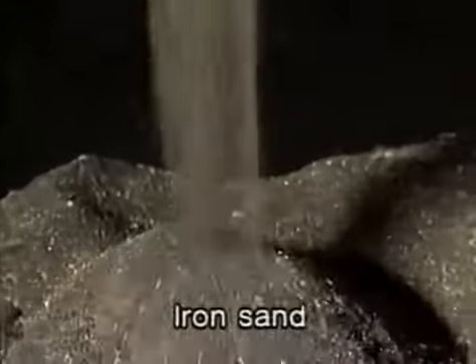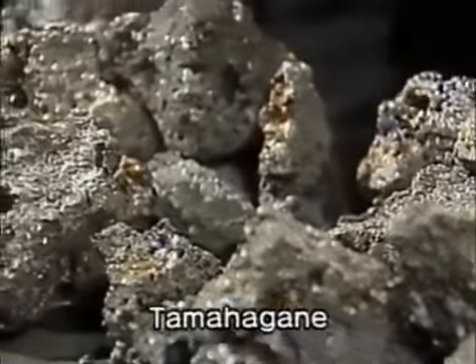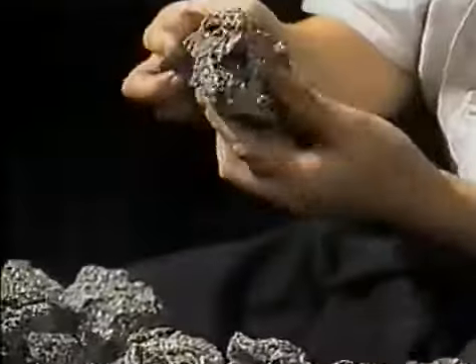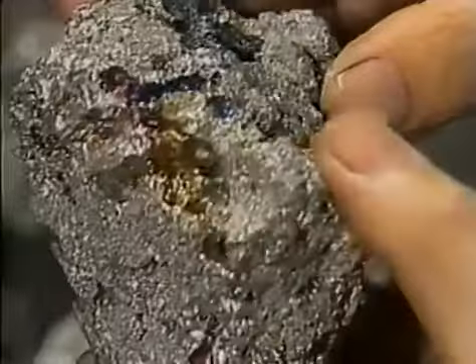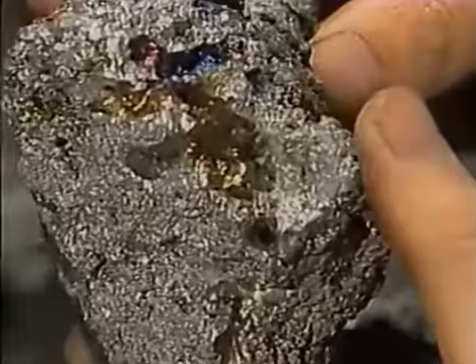The other key characteristic of Japanese swords is the use of a raw material known as tamahagane. This special kind of Japanese steel is made by heating satetsu, or iron sand, over charcoal at comparatively low temperatures, resulting in a steel that is low in impurities. Elsewhere in the world, steel from blast furnaces is used. In Japan, rather than using coke, the smelting of tamahagane is done using charcoal throughout. The swordsmith has to distinguish between the different pieces of steel and pick out carefully those best suited to making a sword.